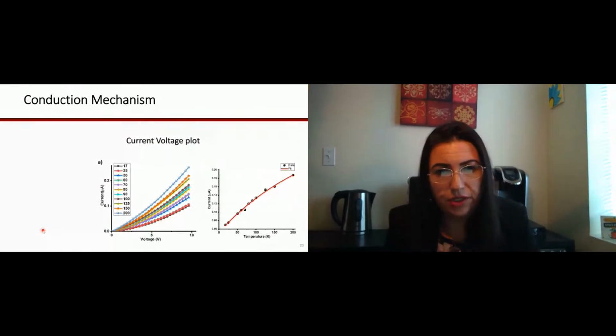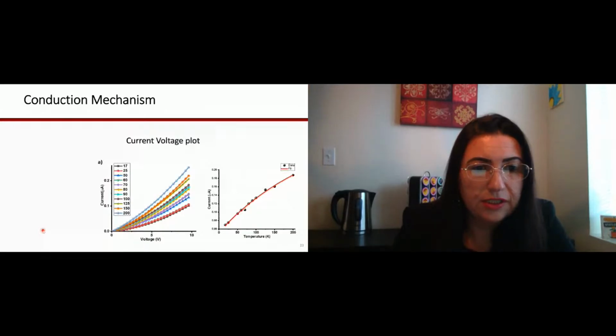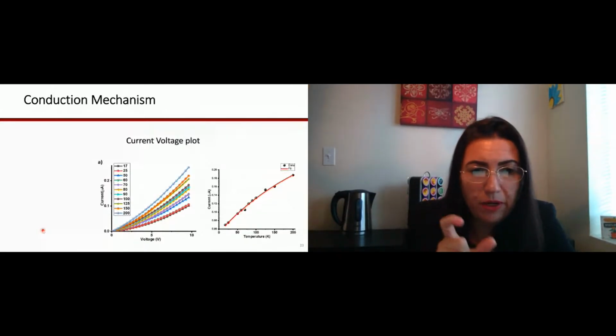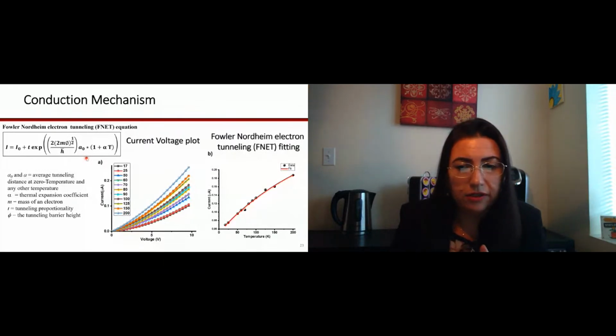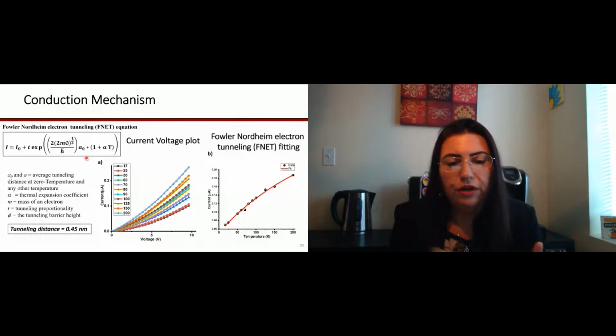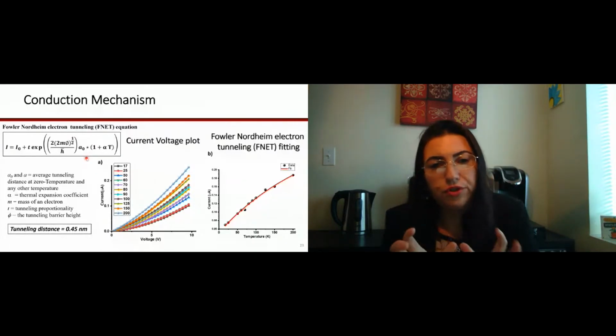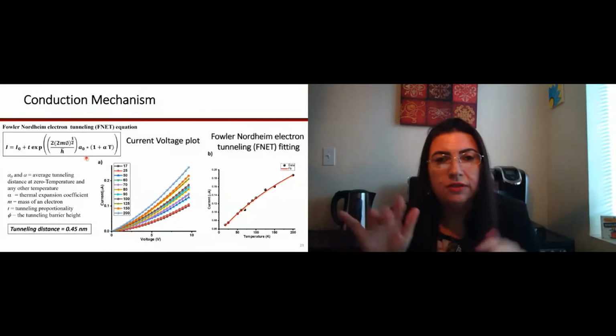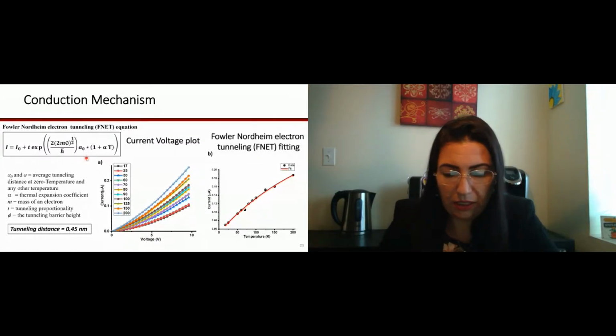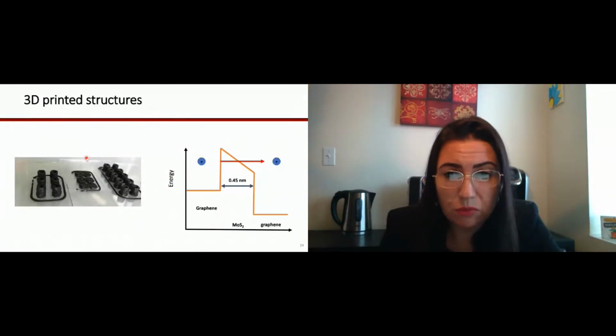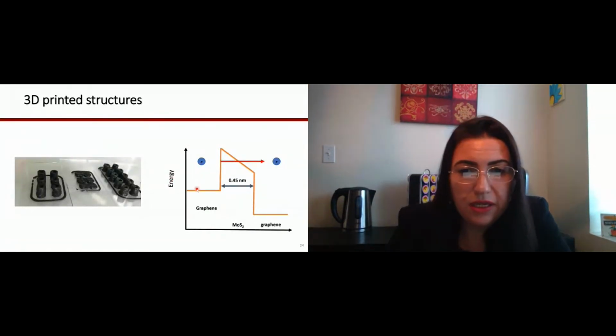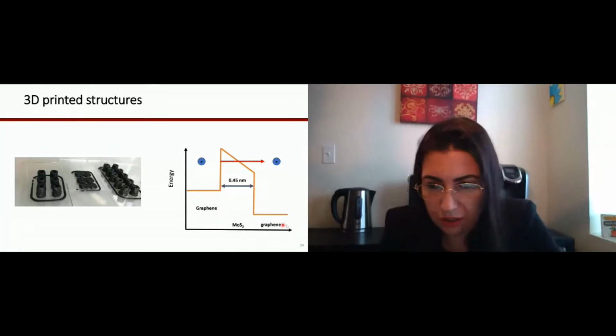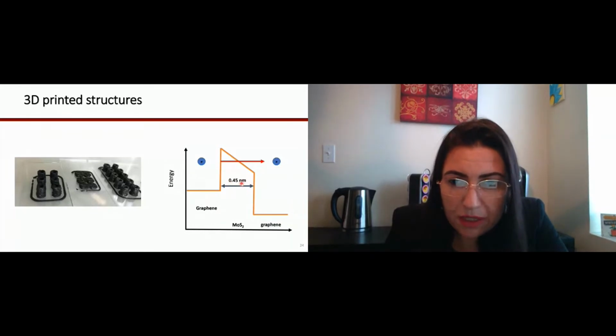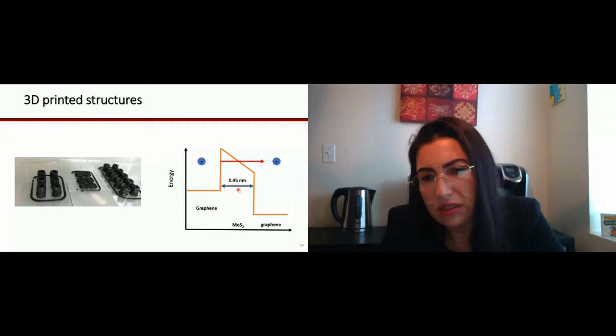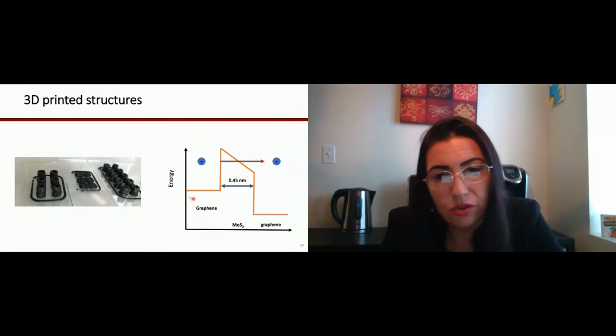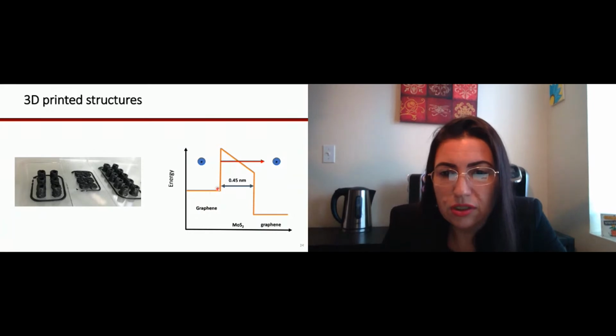And the other thing that we can do with the same type of electronic study is the following, and that is a naught over here. This a naught is the average tunneling distance, how much distance you have between one graphene and the other. And to understand this 0.45 nanometer, it's really important to determine if the electrons are hopping or tunneling through. And the data that we get here is really important for us in this case. So as you see here, we have a graphene sheet here, and we have another graphene sheet. The 0.45 that I mentioned is nothing more than the MoS2 distance that we have between one graphene sheet and the other. So the electron is coming here, and it needs to tunnel through the MoS2.